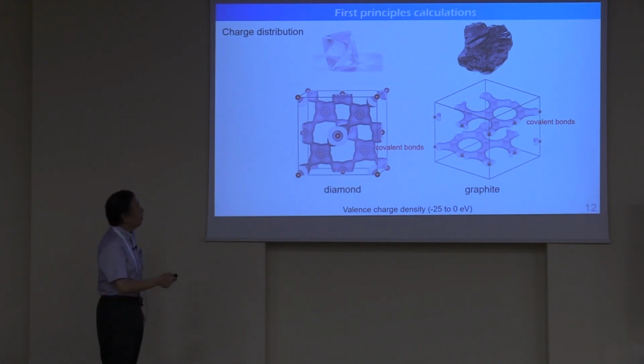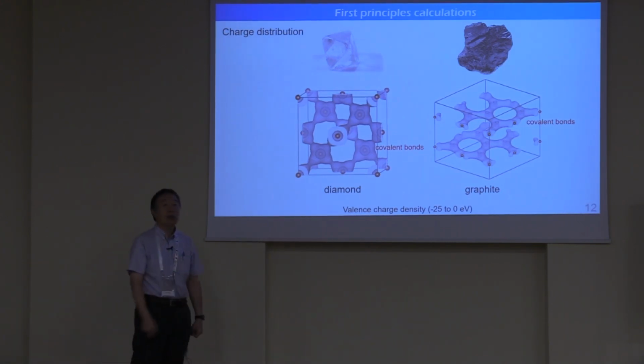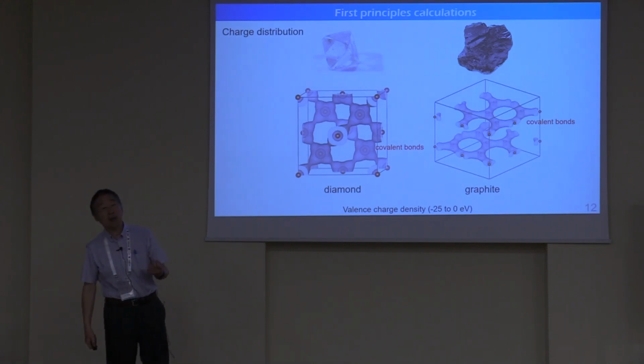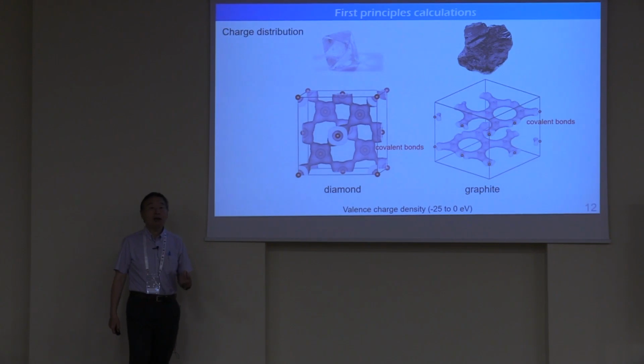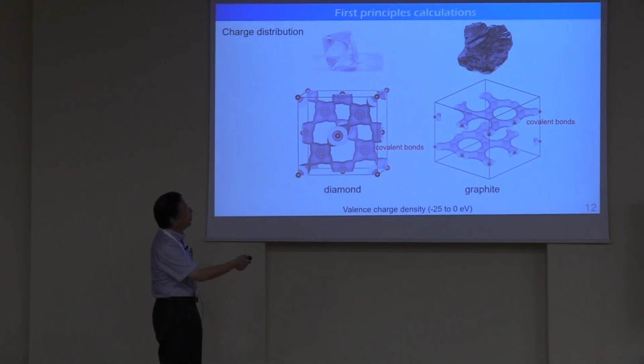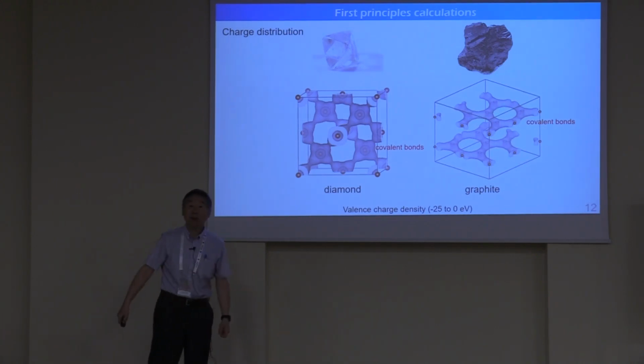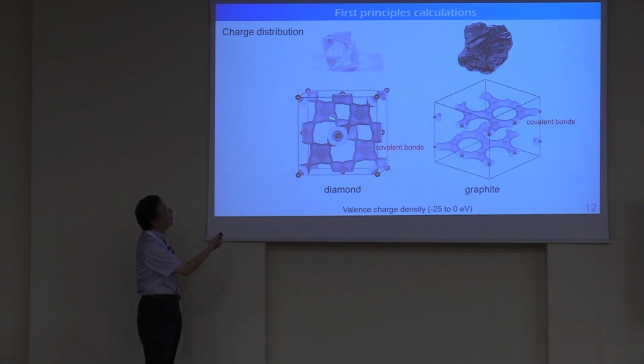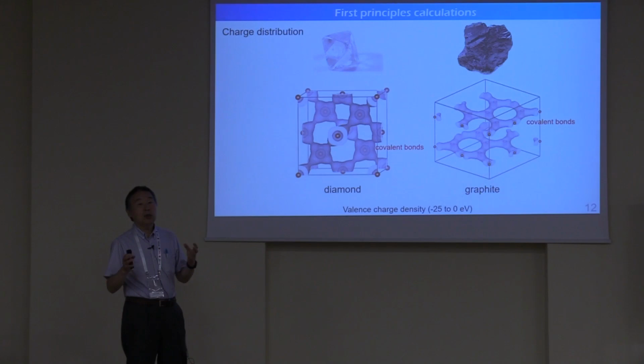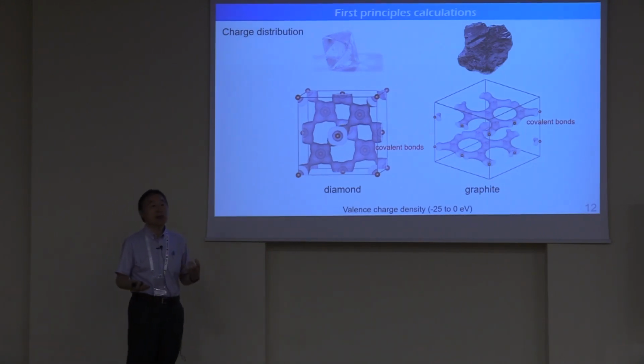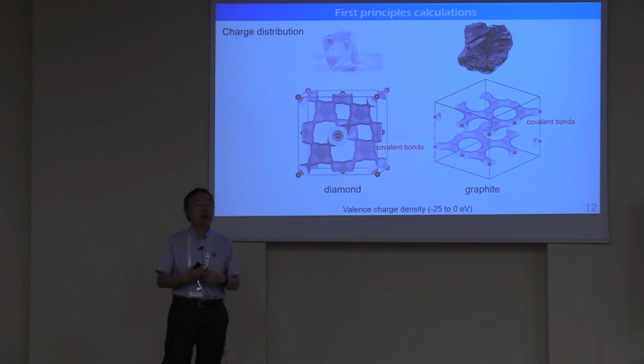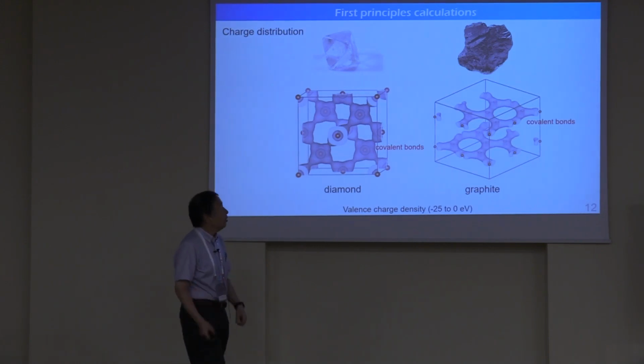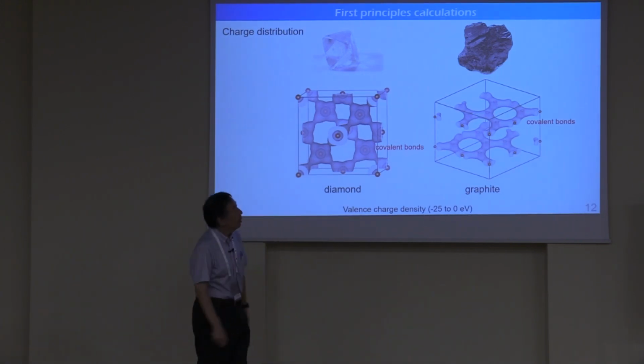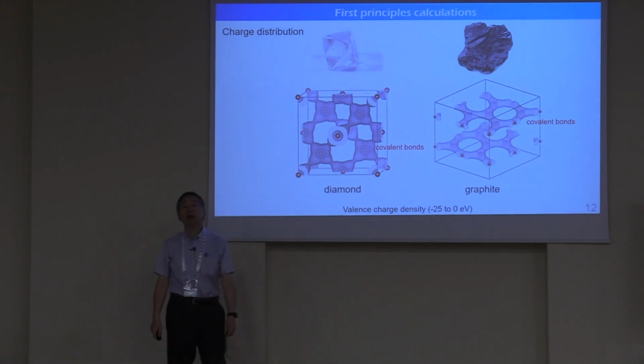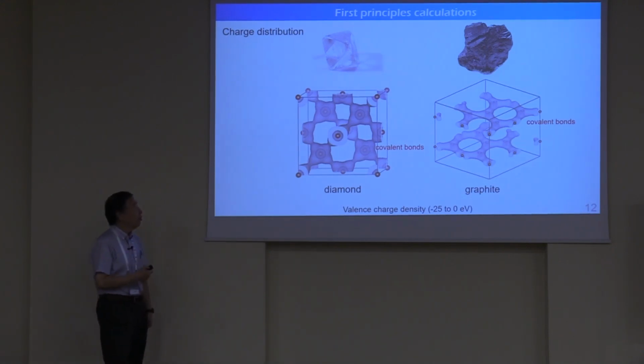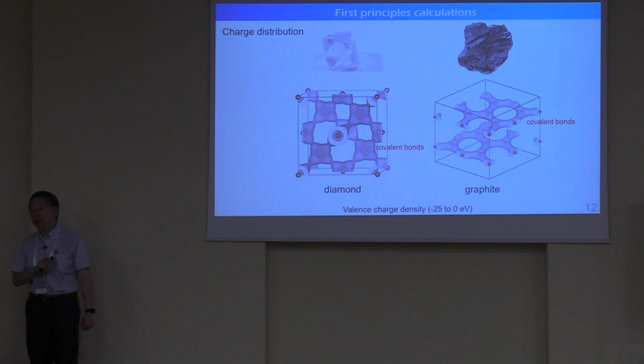And many people think that diamond is very hard. Graphite is soft. Actually, graphite is used in a pencil, but it is true that it is soft. But actually, graphite is not so soft. If you look at this in-plane bonding, this is very strong bonding, which is much stronger than the bonding here. That is the reason why you can use carbon nanotube for some structure application. This is very much used for very high strength structure application, because they can use this very strong covalent bond and not using this interplanar, very weak van der Waals bonding. So this type of information can be obtained by the real space charge distribution.